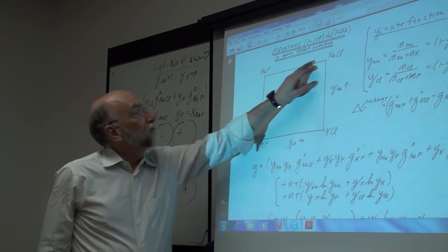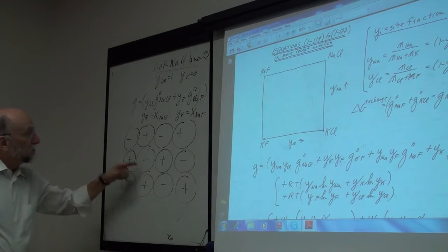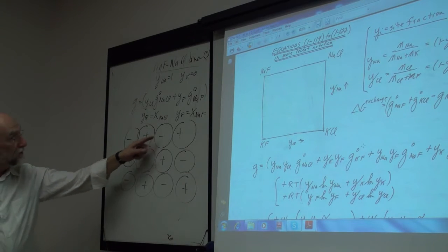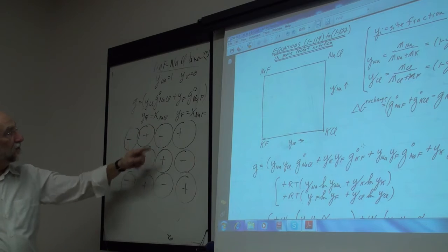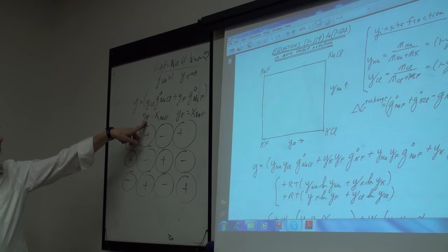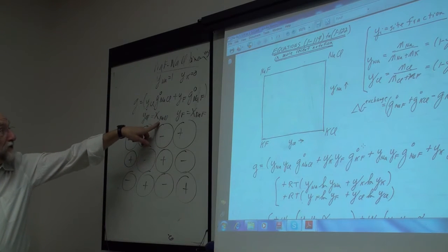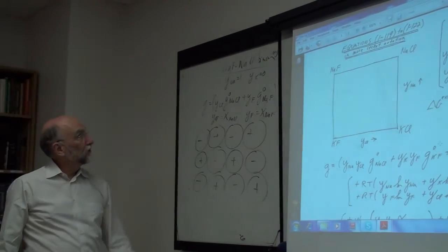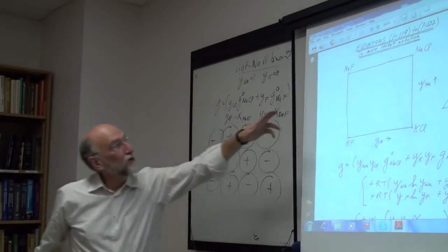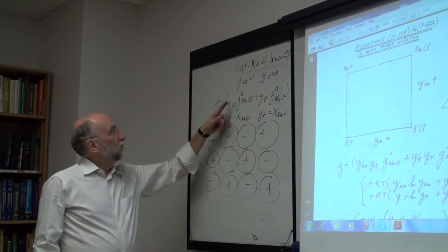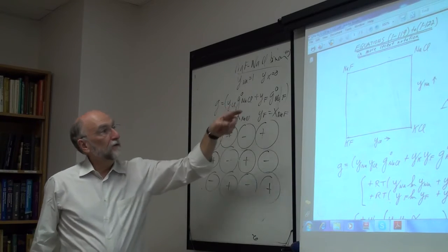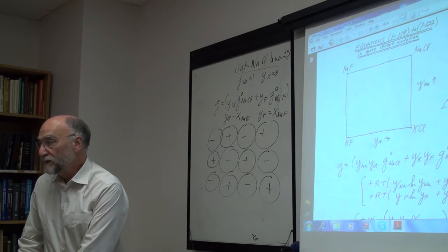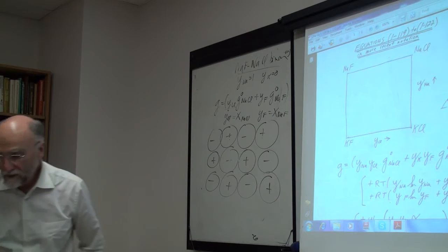If you're going from NaF to NaCl, all the positive sites are occupied by sodium, and you're only mixing fluorine and chlorine on the negative sites. The site fraction of chlorine is the mole fraction of sodium chloride in the binary system, and the site fraction of fluorine is the mole fraction of sodium fluoride. The Gibbs energy goes from sodium fluoride to sodium chloride, just like in any binary system.